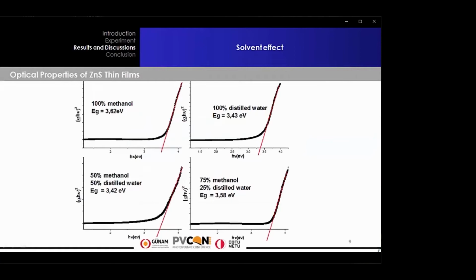From the transmission spectra, we have calculated the optical gap using the Tauc formula, and we can observe that the gap for all films varies in the range of 3.43 to 3.62 electron volts. These values are close to the values reported in the literature.